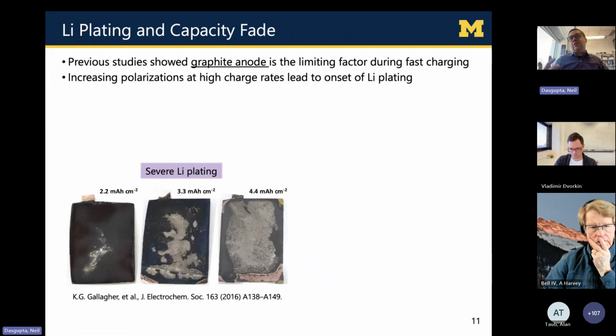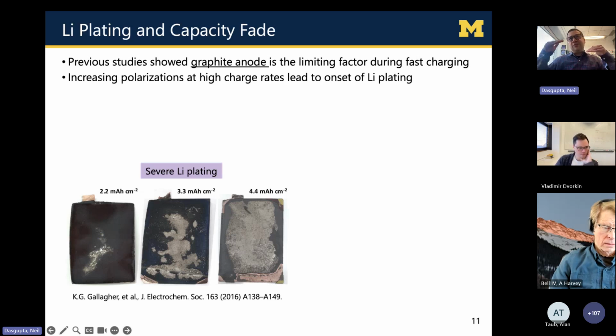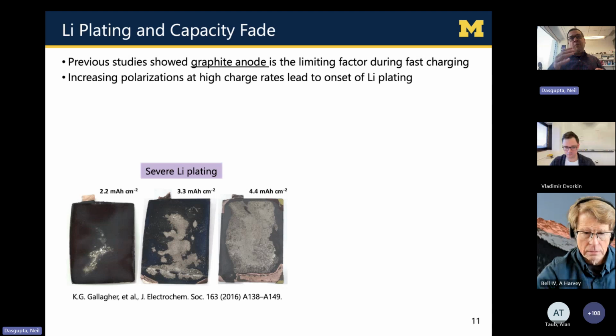And this is something the US Department of Energy realized is a major issue. So over the last 5 to 7 years, there's been a lot of investment in trying to understand the limitations of fast charging and overcome it with various different solutions. What I'm showing here was an early study out of Argonne National Lab where they manufactured these lithium-ion pouch cells. So what you're seeing on this photograph are 3 different graphite anodes after a battery was fast charged, and they open it up and take a look inside and take photographs.